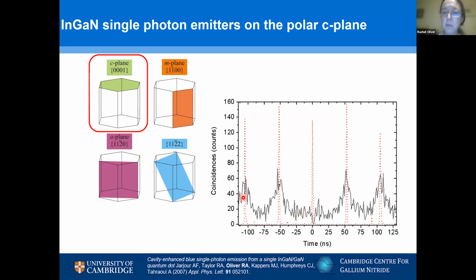But we can see that we've got these pulses and then a nice clear dip at time equals 0. The red dashed line is the laser that we use to excite this device. It's an optically pumped device at this stage. And you can see that doesn't have this nice deep dip at time equals 0, because the laser isn't a single photon emitter. And we've got the signature that we were looking for, proving that these indium gallium nitride quantum dots act as single photon sources.